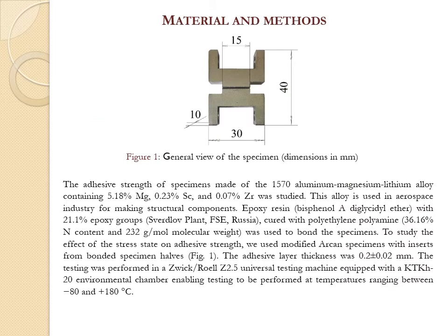The adhesive strength of specimens made of the aluminum-magnesium-lithium alloy was studied. Epoxy resin was used to bond the specimens. To study the effect of the stress state on adhesive strength, we used specimens with inserts from bonded specimen halves, as shown in picture 1. The testing was performed in a Zwick universal testing machine equipped with the environmental chamber.